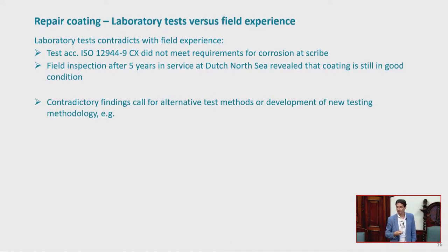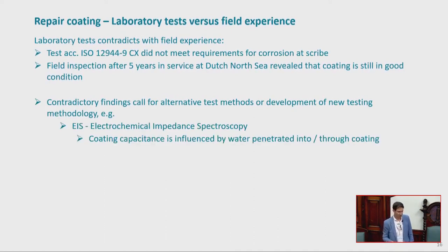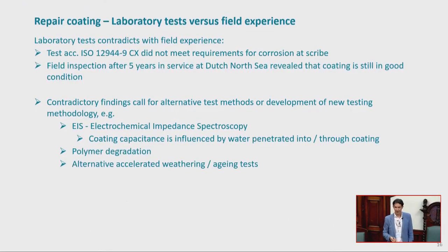So here we have found a contradiction. We know in reality it works, but when we did the test in the laboratory, we actually found penetration of water underneath and a complete disbondment of the system. So you can question, is the coating bad? But it did work in reality. And of course, our preference is that it works in reality rather than in the lab.